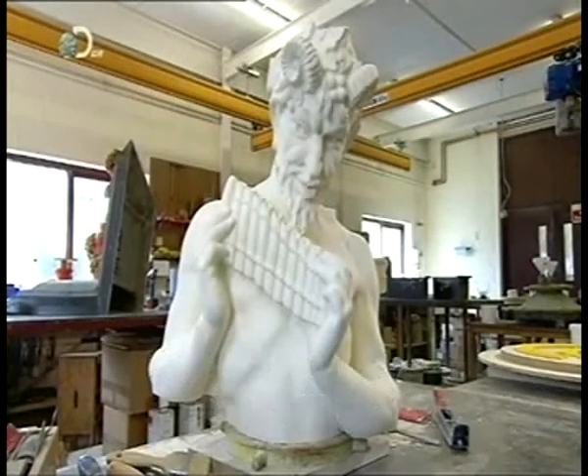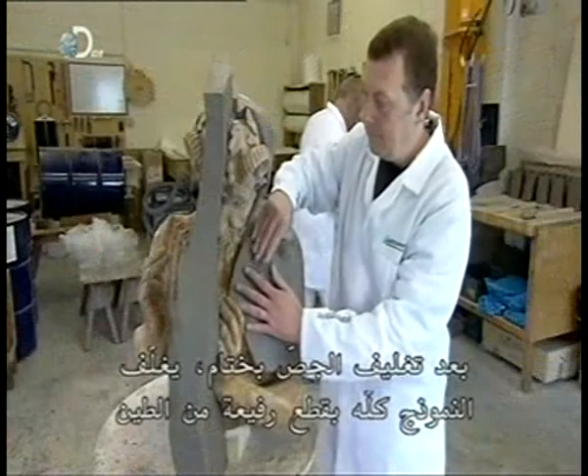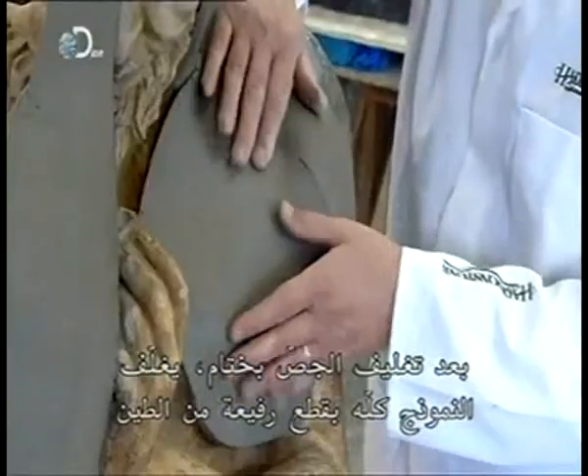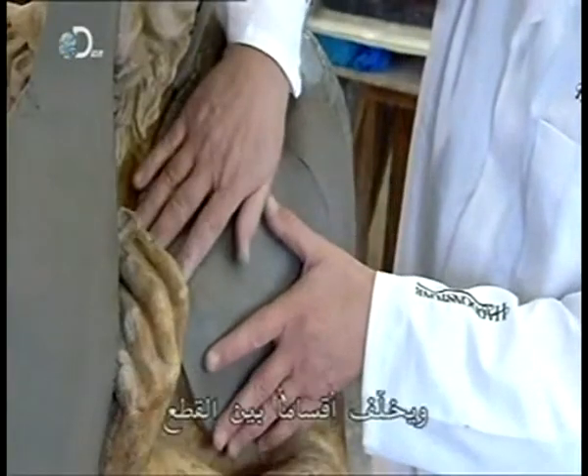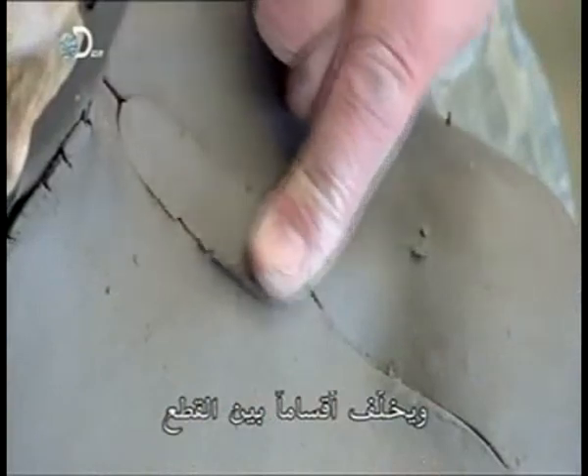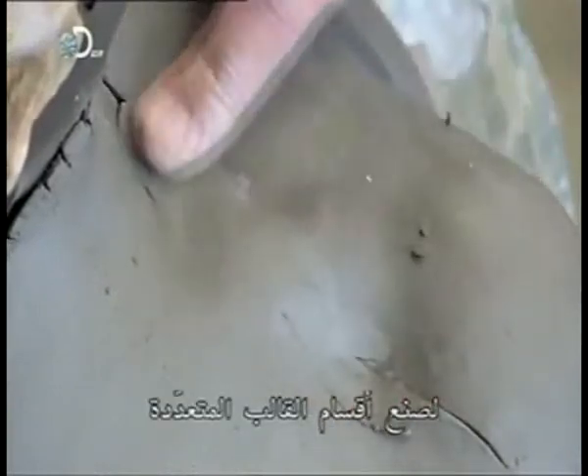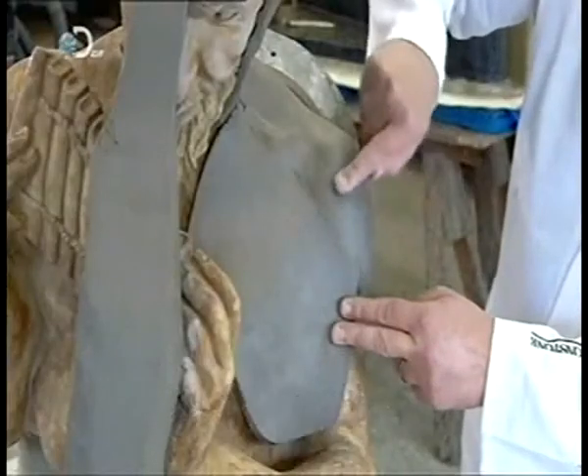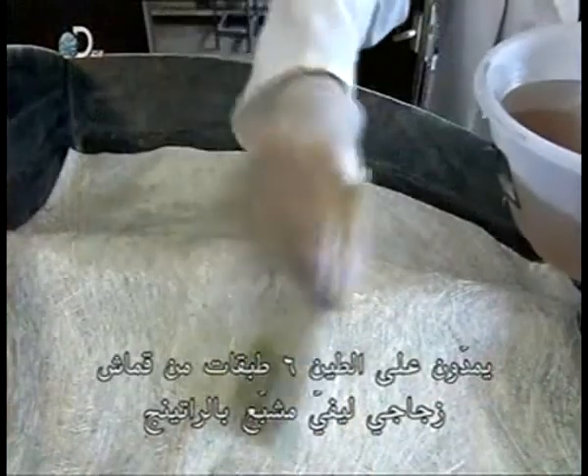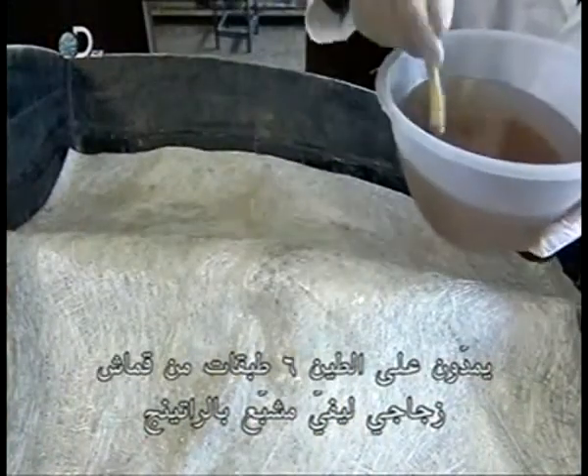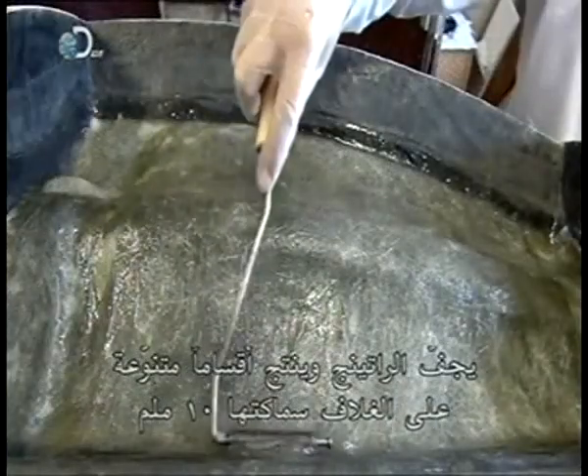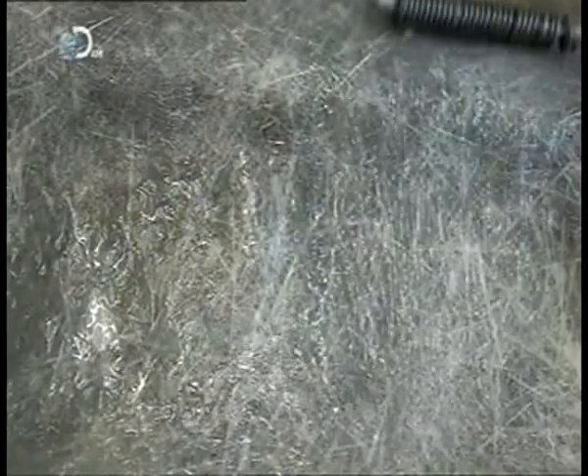After coating the plaster with a sealer, they cover the entire model with thin strips of clay, making certain divisions between strips to create the production mould's various sections. Over the clay, they apply 6 layers of fiberglass cloth saturated with resin. The resin cures, producing a 10mm thick multi-section case around the clay-covered model.